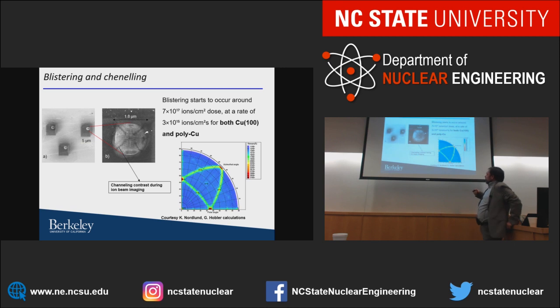And so fortunately, Gerhard Hobler and Kai Nordlund calculated channeling directions for copper in various ways. And you find that in 101 and 011 and so on, they find very strong channeling, and along these different directions, there's strong channeling. And it seems that they match pretty well with our blister, which pops out and then actually shows these channeling contrasts.